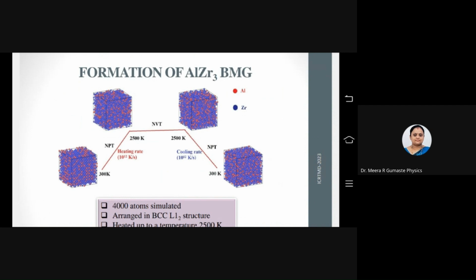On the top left hand side, you can see the structure at 2,500 Kelvin. That's the melted structure. And then we carried out the NVT simulation. That means we have equilibrated the system at 2,500 Kelvin for 1 nanosecond. So that is the right hand side top structure, the melted structure. And after that, the melted structure is quenched at a high rate to make the glass.